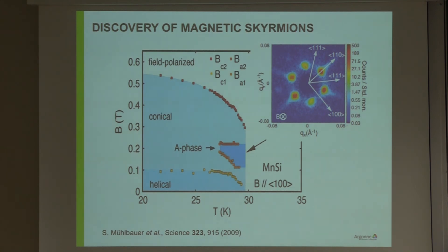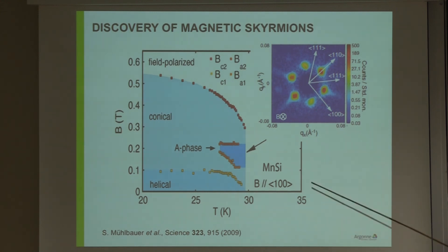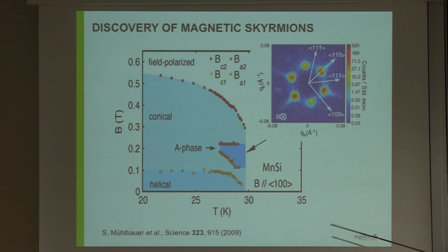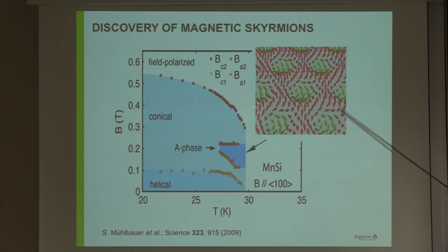Although we've heard a little bit about skyrmions, I want to remind everybody that magnetic skyrmions were experimentally discovered using neutron scattering. For most of my career I've been doing neutron scattering, so it's always nice to see a scattering plot. Basically in this phase diagram of manganese silicide, they found the A-phase — anomalous phase — which had been found for quite a while in systems showing helical and conical phases. With small-angle neutron scattering they found a sixfold symmetry of diffraction spots.